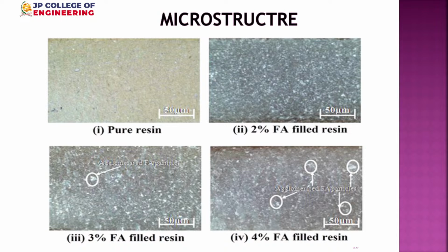So the moment you go for 3%, you can see at some places we get a rounded structure. That is agglomeration of the particles. The moment you go for 4%, again you can see at many places the agglomeration happens. So what we felt is 2% is our better, good dispersion. 3% is okay. But the moment you go for 4%, the dispersion is not uniform. The particles join together and become agglomerates. So this was some kind of an idea. Therefore, either 2 or 3% will be good for better distribution.